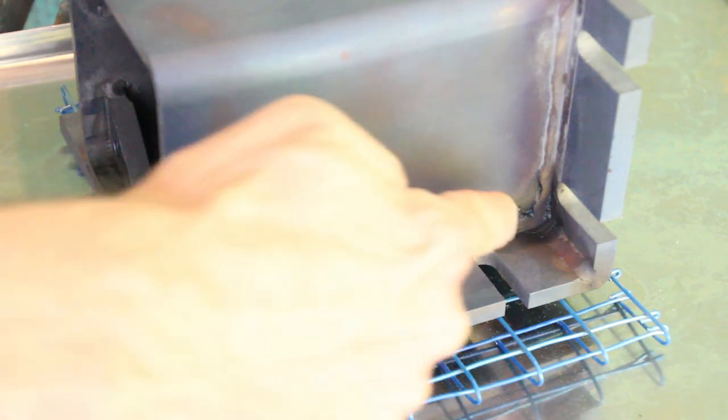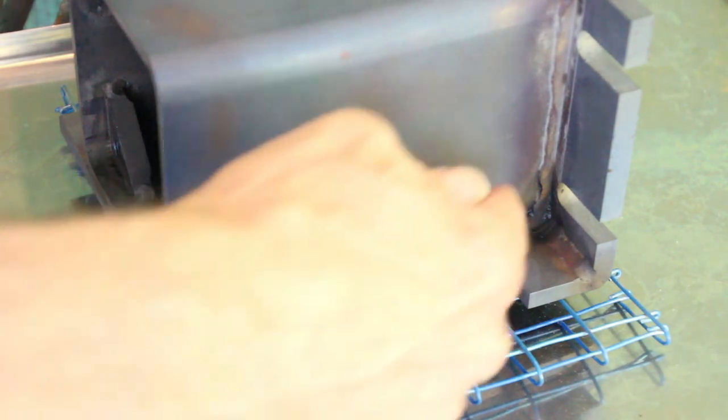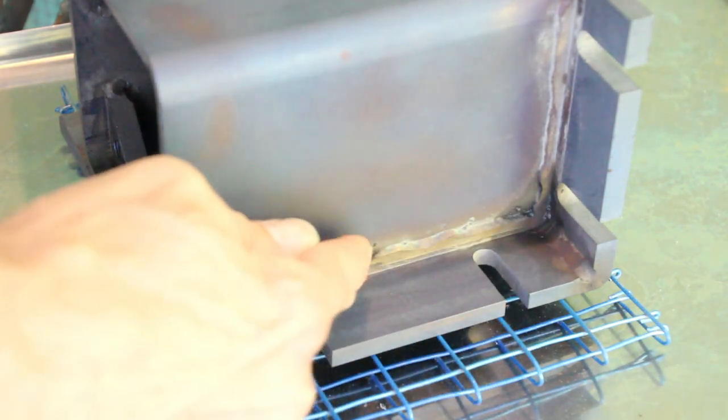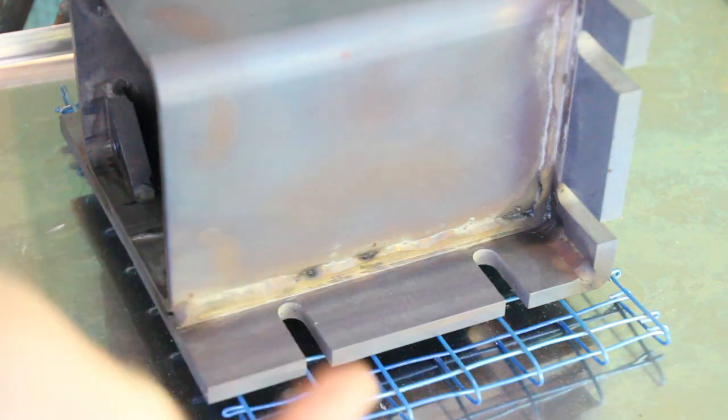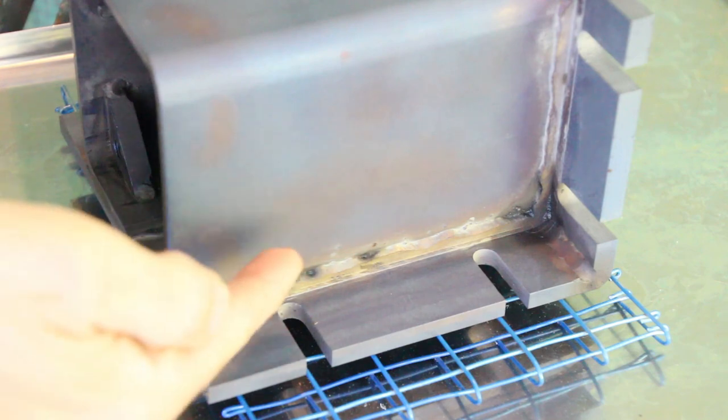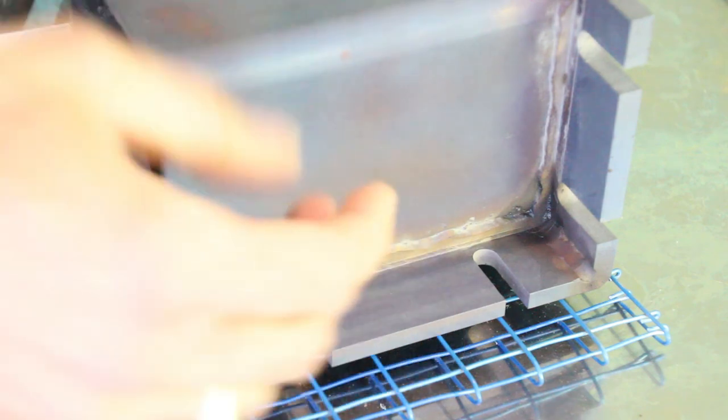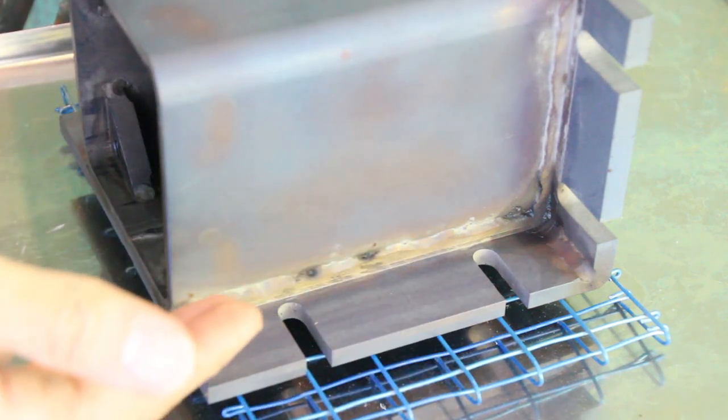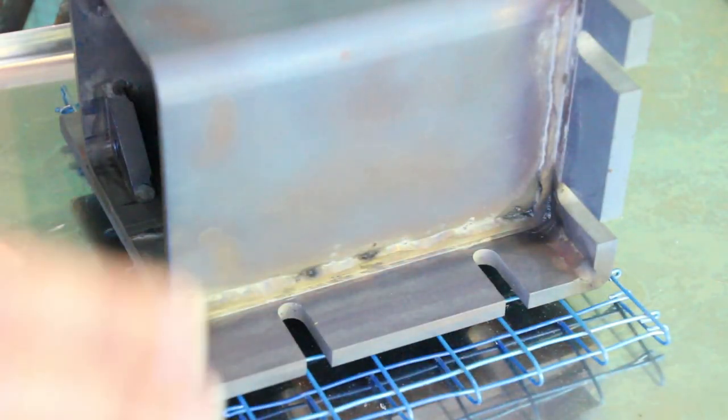What I want to point out is you can see especially dark areas in here—and I'm being careful, I have not touched this with my hands, I'm going to be touching it only with gloves—but you see the dark areas right here, that's where oil was oozing out of these seams during the baking. Oil was trapped in between the pieces of metal and the heat causes that oil to move outward. You can imagine what would happen if that occurred while I was trying to cure a powder coating—oil coming out underneath the powder coating film would just totally ruin the whole thing.